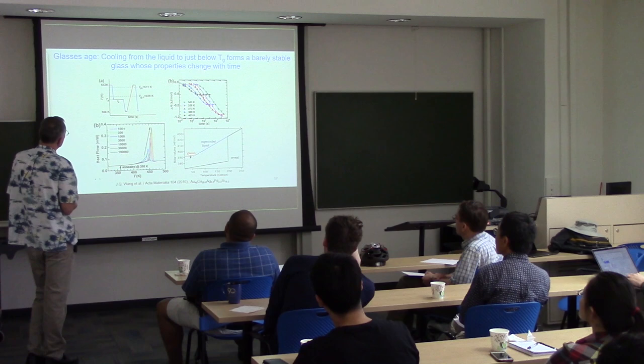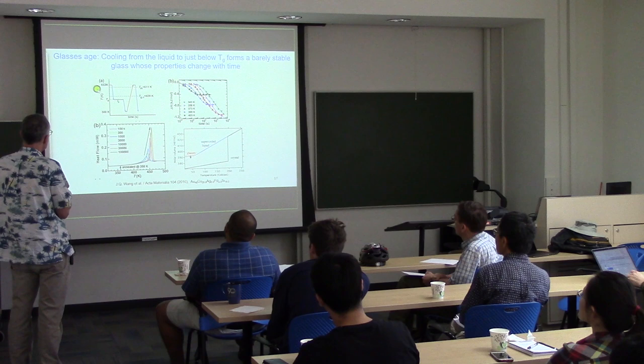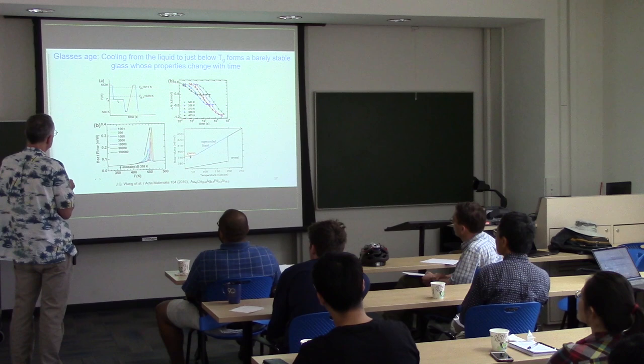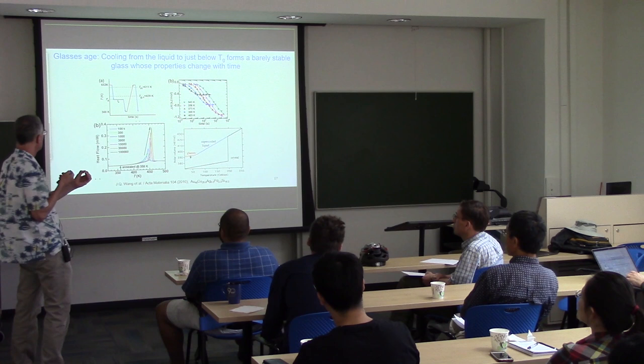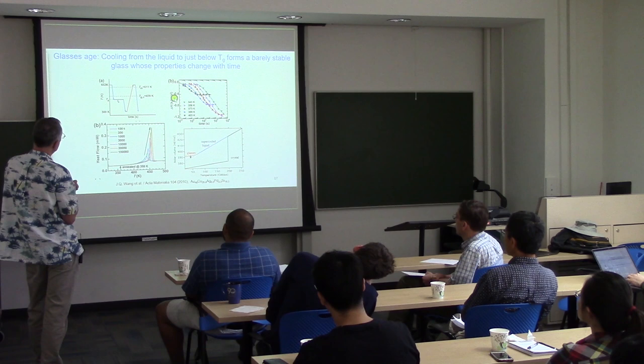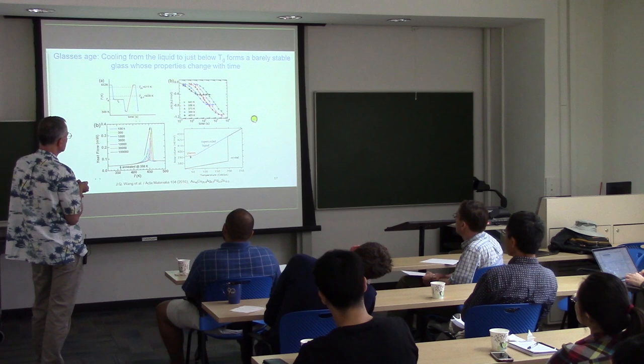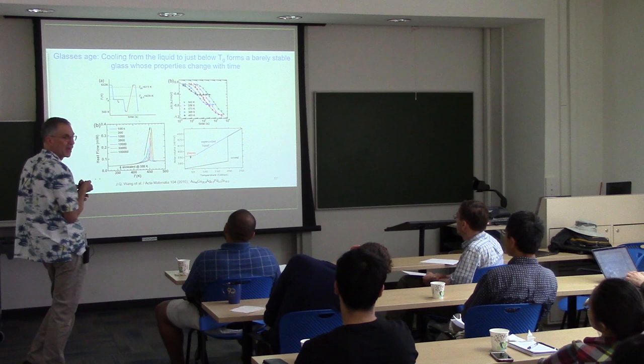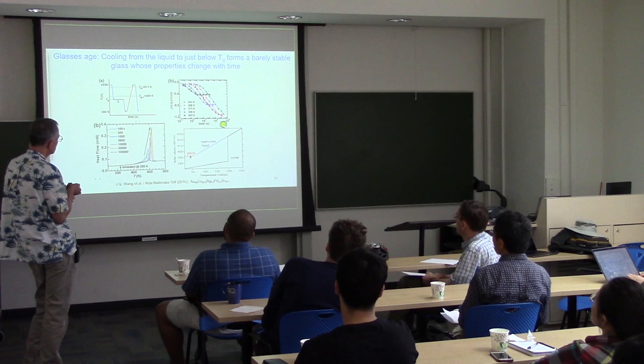So the way this experiment works is you start off with the system at equilibrium above the melting point, okay? You do a very rapid quench to some temperature below the glass transition temperature. You hold it for some period of time, and then the rest of this whole experiment is just measuring what the enthalpy was as a result of that aging profile. And so this panel B here shows you how the enthalpy of the system evolves in time. So I want to make sure you understand this is a logarithmic time scale here. It covers 8 decades. This is one of the nice things that you can do with this flash DSC apparatus. So we have aging times from 10 milliseconds up to something like a week.